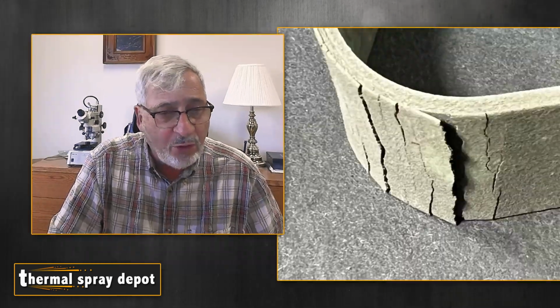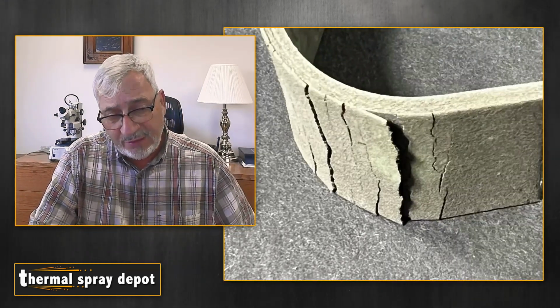Yeah. So again, this is a simple test we can do to convince ourselves that we have the proper media, we're using the right parameters to roughen the surface, and we're using the right parameters on the thermal spray, and we'd have a good coating. In this case, this failed. This is a bad coating.